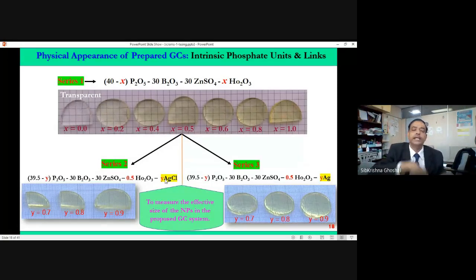If we put silver chloride, heat it in the material, then through a process called coalescence and ripening, it will form the nanoparticle. But if we already buy from Sigma Aldrich or from company Merck high quality silver nanoparticle, we can also dope that, then we can heat it up so that some of the bigger nanoparticle would be decomposed into smaller. So we started with both. On one hand, we let the system form the nanoparticle. On the other hand, we buy the nanoparticle and forcefully dope in the system. We wanted to see which produced the better effect. That's what the three series of glasses.